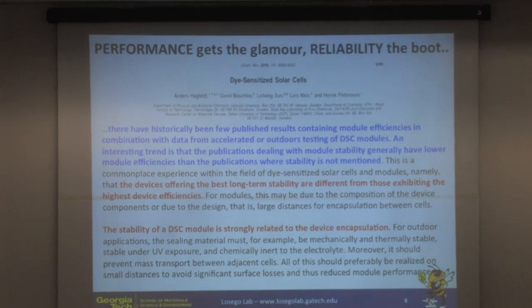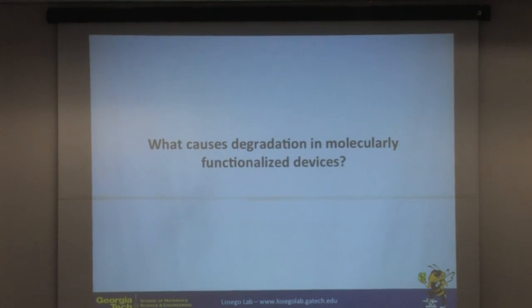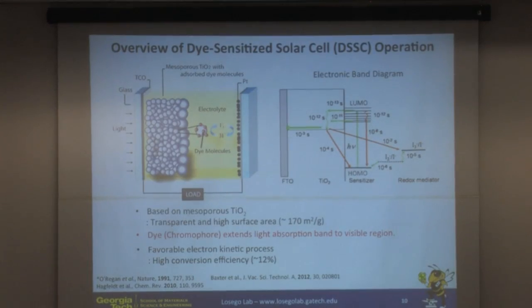The stability of a DSC module, they conclude, is strongly related not to how it's designed, but rather how the device is encapsulated. So we'll talk a little bit more about the importance of encapsulation up to this point, and why that's been used really to get reliability, not inherently changing the device design. Okay, so before we do that though, let's look at what causes degradation in these molecularly functionalized devices.